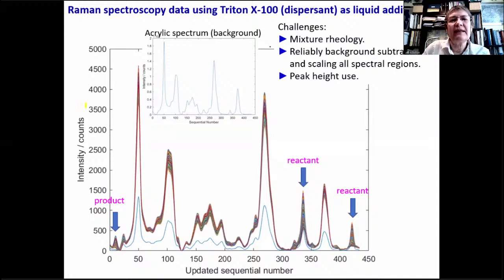So most of that signal is actually the acrylic, and the acrylic has to be subtracted in a reliable manner. It has to be scaled and subtracted from each of the hundreds of spectra that can form one kinetic run. So this is another challenge, and we can see that the signal of the reactants, this one is the reactant and this one is the other reactant, is just a small fraction of what we measure, and this one is the product, and they have to be separated at different wave numbers.